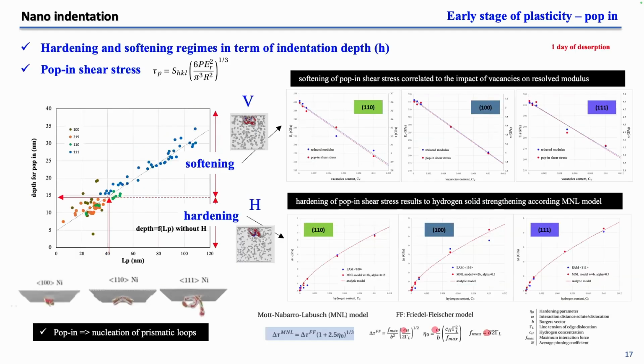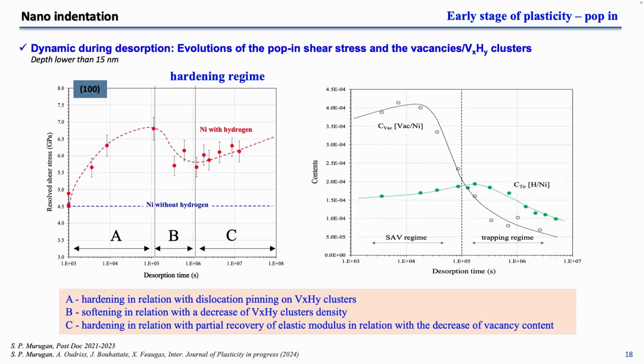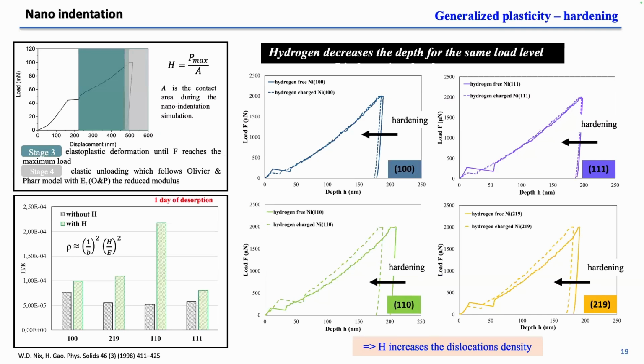And if you try to explain that, we try to correlate the softening with the decrease of the elastic modulus as a function of concentration of vacancy, and the hardening, the solid solution strengthening, is well modeled by the model. We don't describe that, but it is during the desorption. The last result is the fact we have hardening in each domain, each orientation for large deformation, which is linked with a simple model to the increase of density of dislocation. And this dislocation density increases when we add hydrogen in all the orientations.